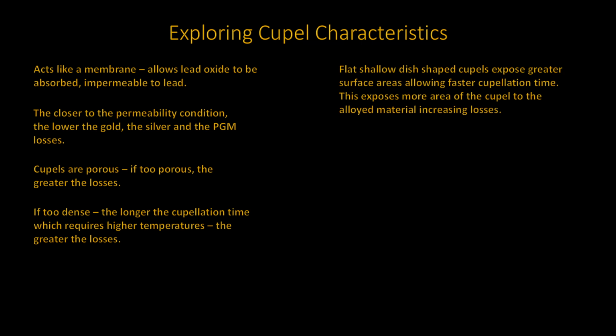The shape of the cupel will also cause additional losses. Flat, shallow dish-shaped cupels expose greater surface area, which in turn allows for a faster cupellation. The problem is in the fact that it also exposes more area of the cupel to the surface of the alloyed material, which increases loss by absorption.